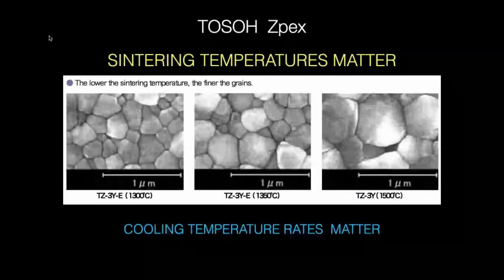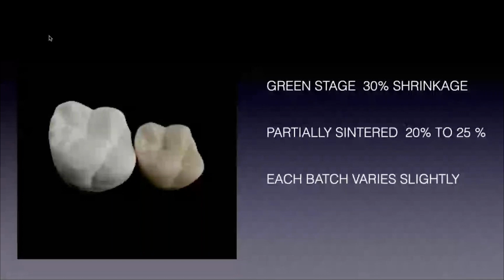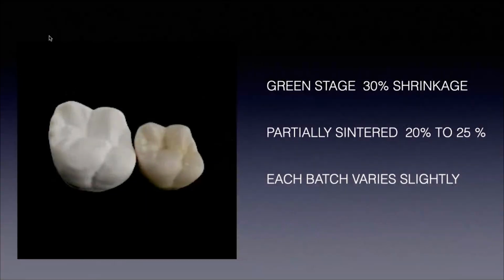You can see at 1300, you can see the grain size change as you go up in temperature. So this is what you have to remember too, that not only the sintering temperature matters, but the cooling temperature matters as well. The slower, the better. So initially you have about a 30% shrinkage from the zirconia, partially sintered 20 to 25%. And so that's a before and after.